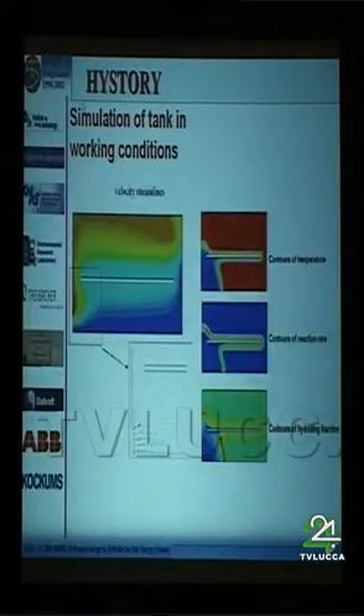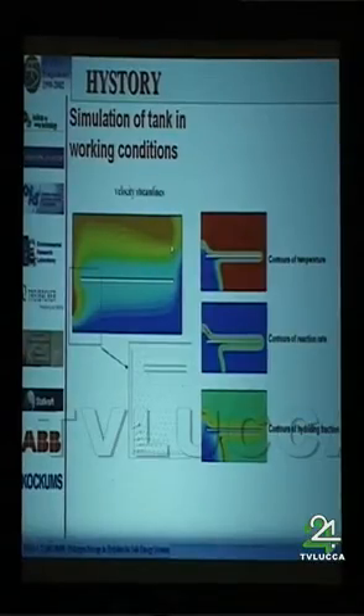For the high temperature metal hydride, magnesium, we have also developed the same type of simulation program. Here you can see, for example, the cooling system in a tank. We can simulate in time, second by second, what happens with the distribution of temperature in the tank around the cooling system when hydrogen is introduced under pressure, the contour of reaction rate, the contour of hydrogenation fraction, and so on. So now we have nice information about how to build or optimize a tank at the scale of a laboratory.